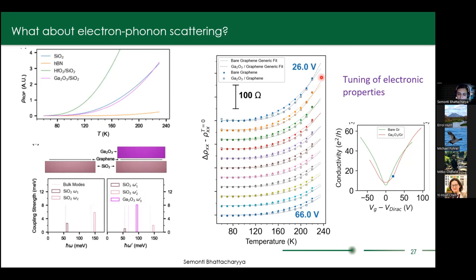The gate voltage dependence arises because the coupling constant is influenced by the carrier number density through electron-phonon screening. From this model, we produce a graph that mimics the behavior of our experimental data. The cases shown are bare silicon oxide graphene, gallium oxide–covered graphene, and graphene on hexagonal boron nitride, which would show the greatest reduction of remote optical phonon scattering — but large-area hexagonal boron nitride that can be easily transferred is not yet available.